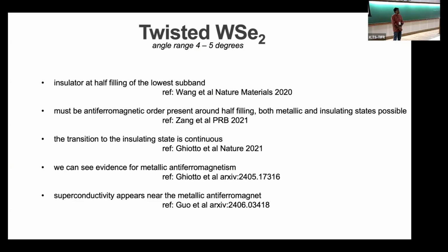Yeah. And I also wanted to know, in this superconducting phase, if you apply a strong magnetic field and suppress the superconducting state, do you see any antiferromagnetic fluctuations persisting in the normal state in that region? Yeah, that was one of the slides I flashed: if you go to 100 millitesla where superconductivity is suppressed, and you look at the phenomenology, you see evidence in the Hall effect for this Fermi surface reconstruction. And so, yes, indeed, we do think so. I see. Thank you.